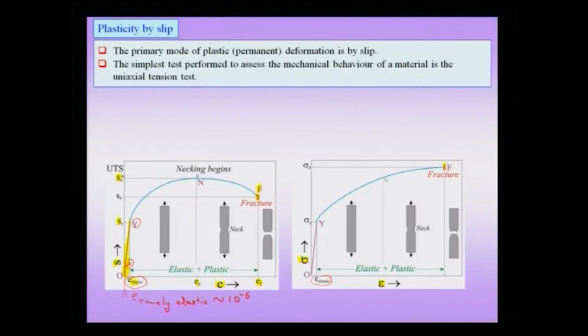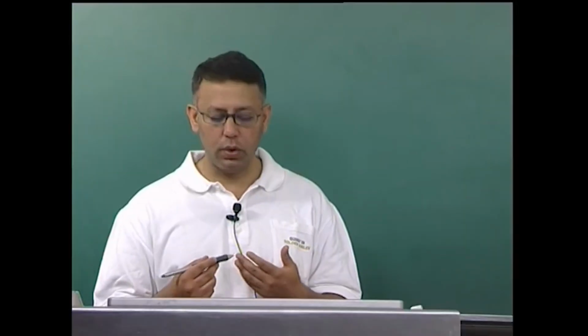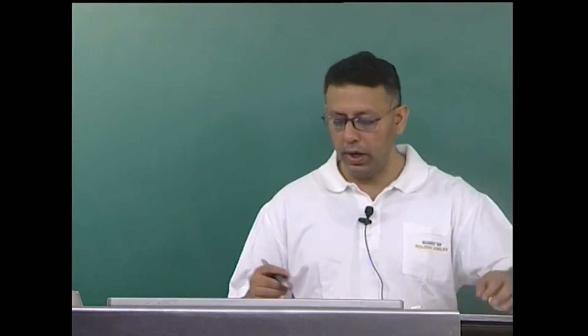Now, if I carry on my uniaxial tension test beyond this point Y, then I see that the curve goes up in the case of the engineering stress strain diagram and starts to come down. This peak is where we attribute the formation of a neck, and this neck is forming because there is localized deformation. That means, the deformation is not spread across the entire gauge length, which I can call L0. So, there is a localized deformation, and this localized deformation finally leads to fracture, and the material separates into 2 halves. And in a ductile material, typically you will observe something known as a cup and cone fracture, and of course, in extremely ductile materials you may even observe something known as a rupture, wherein the specimen thins down to a point and then it fails.